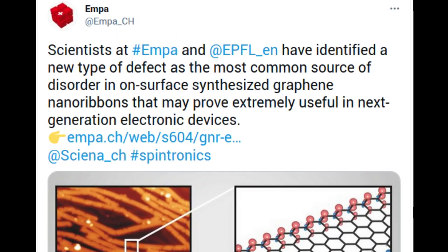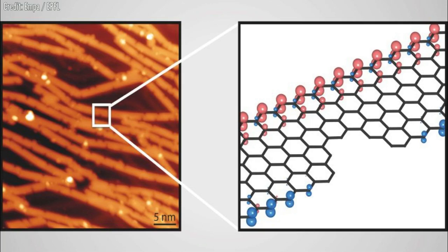Scientists at EMPA and EPFL Switzerland have identified a new type of defect as the most common source of disorder in on-surface synthesized graphene nanoribbons, a novel class of carbon-based materials that may prove extremely useful in next-generation electronic devices. The researchers identified the atomic structure of these so-called bite defects and investigated their effect on quantum electronic transport. These kinds of defective zigzag-edged nanoribbons may provide suitable platforms for certain applications in spintronics.